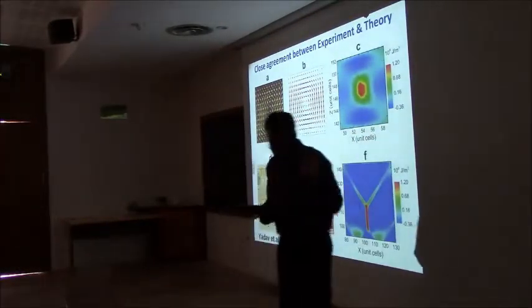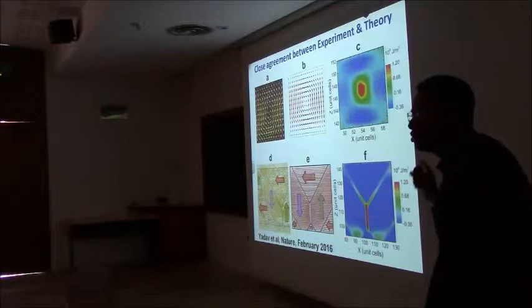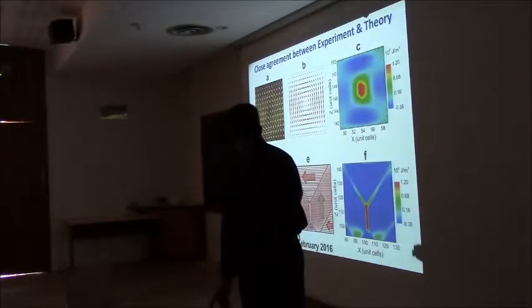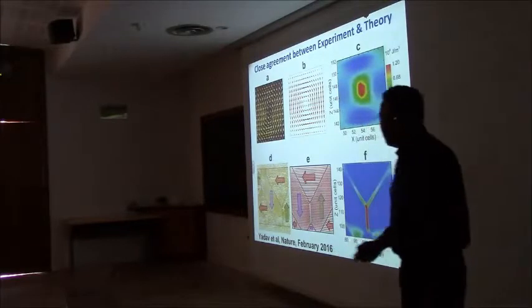Okay, so let's capture this, and we'll get back to Vincent's question in the next segment. So what we can say for sure now is that for certain dimensions of these superlattices, of the strontium titanate and lead titanate layers, you do form this vortex-like structure. That's the calculation, that's the experimental image, that's the energy distribution. These are very different from the classical domain wall structures. If I now coarsen my superlattice, this is a much thicker, about 15 to 20 nanometer thick lead titanate layer, these now become classical.